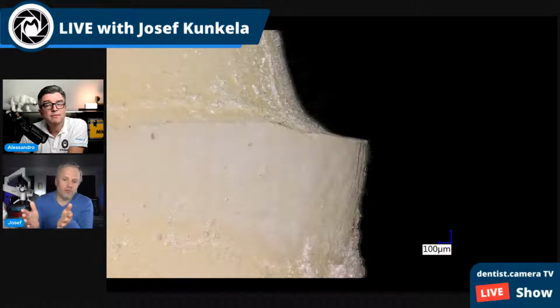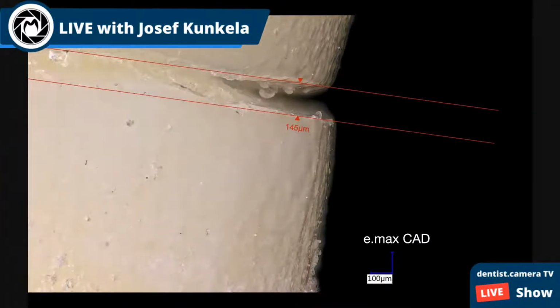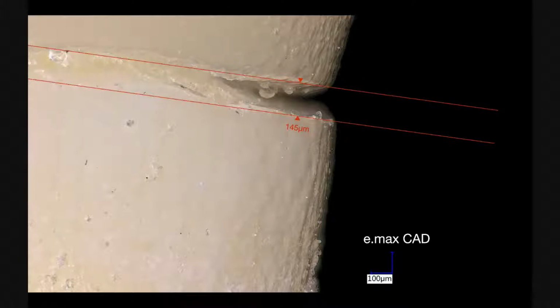And this is how usually the preparation is prepped, with number 010. That means it's a 0.5 millimeter thick shoulder preparation. And I have milled the most popular material, what I have read in the CAD CAM magazine, lithium disilicate, and the fit. And you can see, because of the material, lithium disilicate is very hard for milling, and many times chipping appears around. You can see that there is a gap of 145 micrometers.